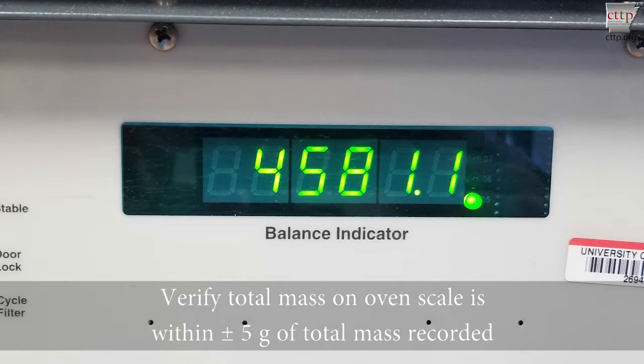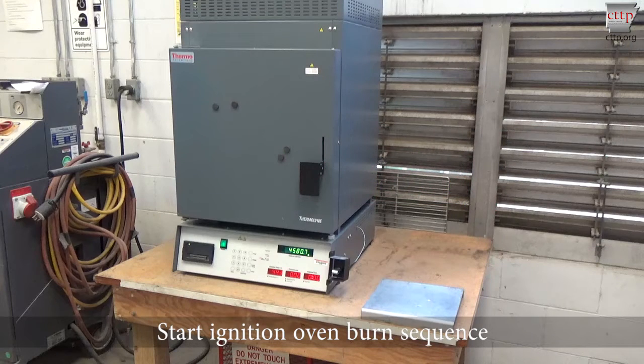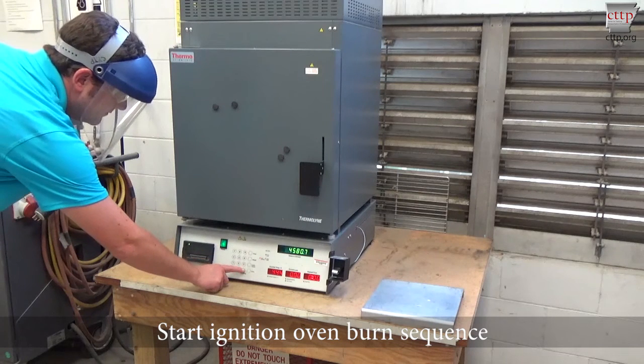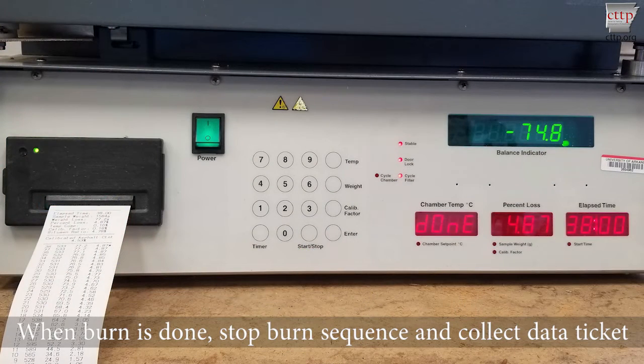Verify that the total mass of the basket assembly and sample shown on the oven display is within 5 grams of the total mass recorded from the external scale. If not, reposition the basket assembly to eliminate rubbing or check the scale calibration. Once the total mass is verified, start the ignition oven burn sequence by pressing the Start button. The scale will zero and the asphalt coatings will begin burning off the aggregate. The mass loss may be monitored on the oven display. When the ignition oven detects no additional loss over a 3-minute time period, the burn is complete. Stop the burn sequence and collect the data ticket.